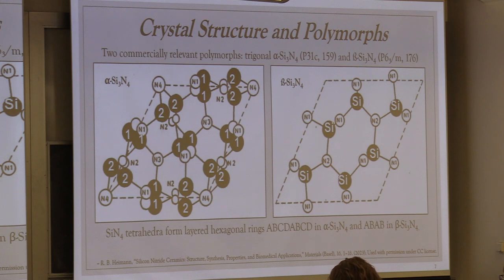Okay, so in terms of the crystal structure of silicon nitride, there are really two relevant forms. There are actually three phases, but two of them are commercially relevant. They're alpha silicon nitride, which is shown on the left, and beta silicon nitride, which is shown on the right. The alpha phase is what is generated in basically a powder form, and it irreversibly converts to the beta phase upon heating above about 1500 degrees C. Both alpha and beta are stable phases at room temperature.